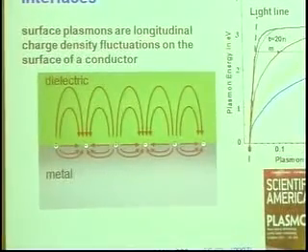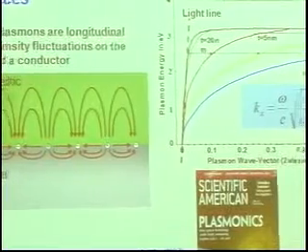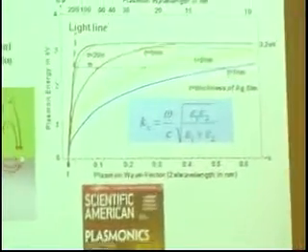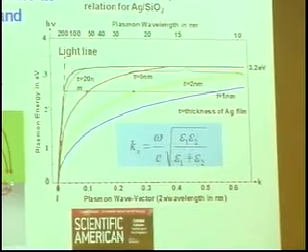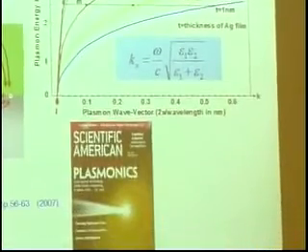And as we approach the natural frequency for oscillation of electrons in the metal, this wave becomes highly dispersive. The group velocity bends over and becomes very small. The wave slows down, and there's substantially increased absorption. And we can tune this dispersion relation by changing the thickness of the metal and various other characteristics, the dielectric constant of this dielectric, and so forth.